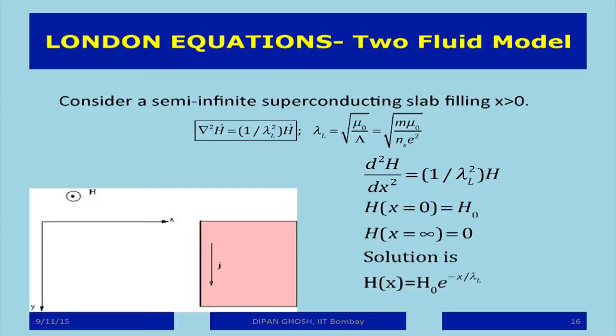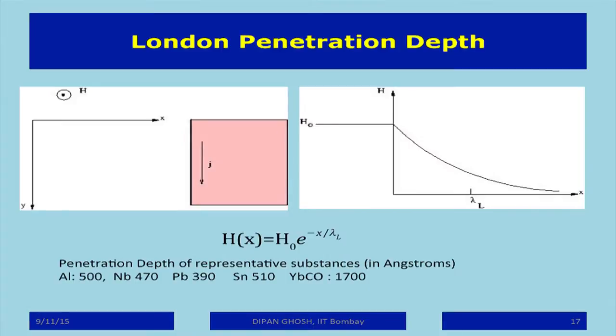Okay? And compare it against these. The typical penetration depth, as one sees in the samples, is given here. That's about, for aluminum, about 500 angstrom. It's a very small depth to which the field effectively penetrates.